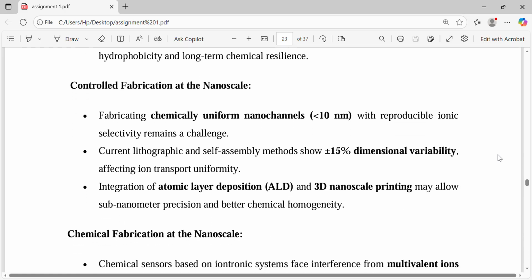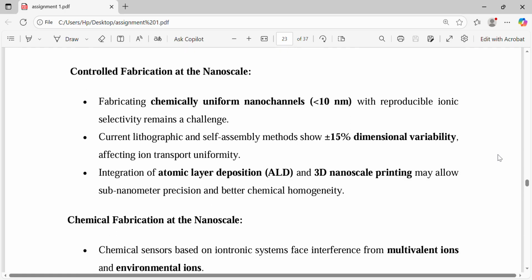Controlled fabrication at nanoscale. Fabricating chemically uniform nanochannels less than 10 nanometers with reproducible ionic selectivity remains challenging. Current lithographic and self-assembly methods show plus or minus 15% dimensional variability, affecting ion transport uniformity. Integration of atomic layer deposition and 3D nanoscale printing may allow sub-nanometer precision and better chemical homogeneity.